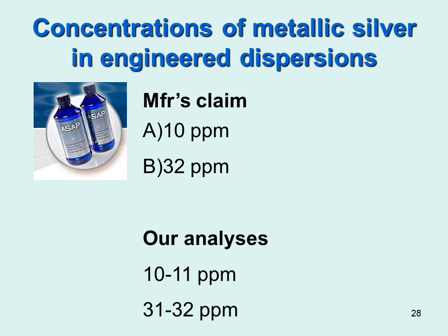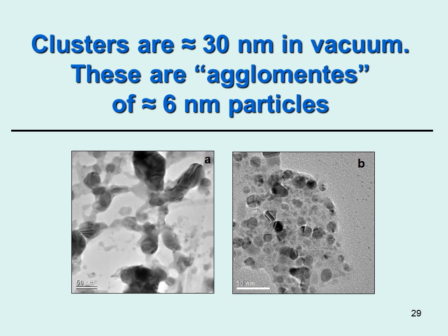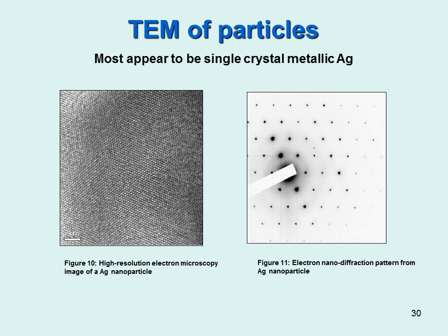How is it doing it? So we looked at this actual sample that was supplied by one manufacturer. I claim nothing that this is the only one that does it. I imagine that most pure aquasols will do exactly the same thing. And we checked them. We checked their chemistry, we checked their structure, and typically they're 30 nanometer clusters, and these are really aggregates which we can see in the cryo-TEM, how they boil off and they leave a structure of about 6 nanometer particles, which actually disintegrate and fly off. And you can see by the HRTEM, they're really metallic silver. There's a little bit of oxide layer sometimes, and so on.